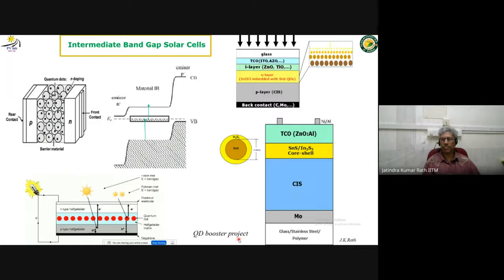It's called the QD booster project. The normal copper indium sulfide cells, but with this emitter, we just wanted to have a four cell structure, and also sometimes we could make different sizes of these quantum dots with multiple layers of quantum dots. And this we tried. It was possible to make this one. Everything also showed slight improvement, but not dramatic improvement. It's only like 1% improvement. So again, it's a concept only.